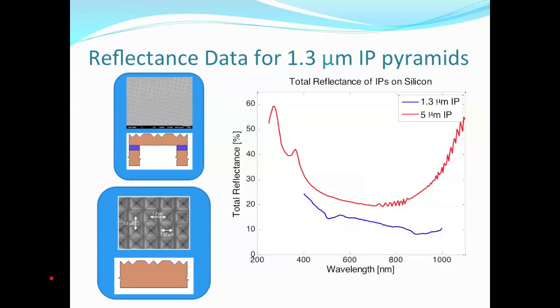Now above 700 nanometers of wavelength, these curves are not directly comparable because we're going to see extra reflection in the membrane due to light being bounced off the back surface. But we can compare them below 700 nanometers, and we can see that using the 1.3 micron inverted pyramids, we're reducing reflection even further. And this is without an anti-reflection coating. Once you put an anti-reflection coating on, we'll get significantly more absorption in the silicon membrane.